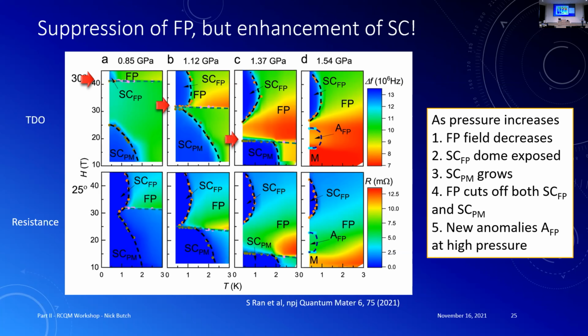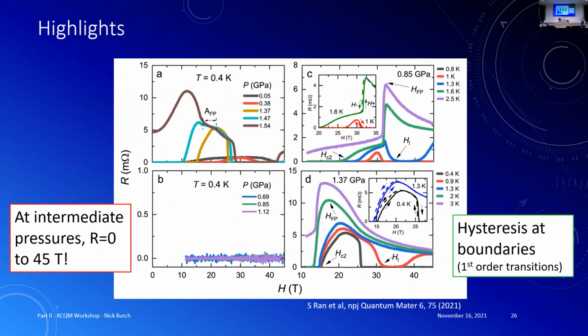Okay, the same story though. So this metamagnetic transition is acting as an upper barrier for this phase, but actually it's acting as a lower barrier from this phase. And if you think back to the data that I showed you at ambient pressure before, I said this is an HC2 curve for the upper transition. It's got a bottom that's defined by the metamagnetic step. So this thing is actually limiting the upper field of this and limiting the lower field of this. So it's the magnetic transition that is really like a hard barrier. It's a fence that the neighbors can't cross.